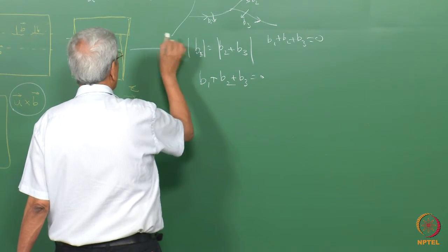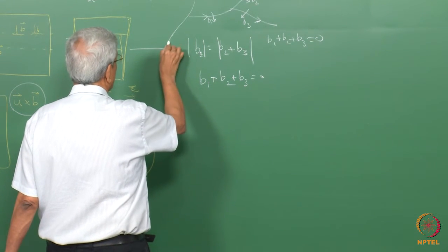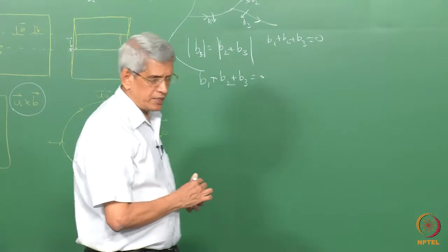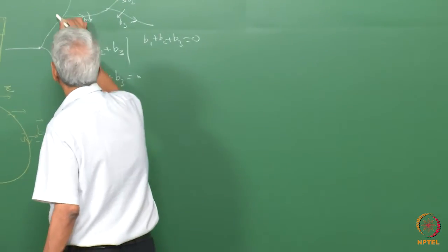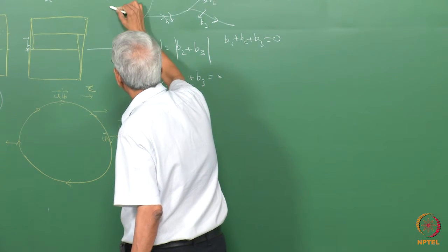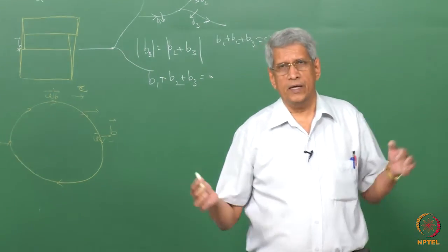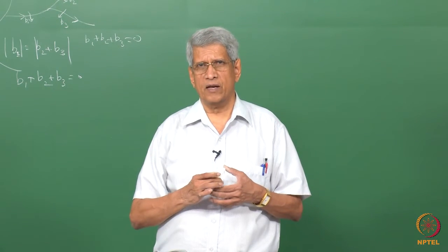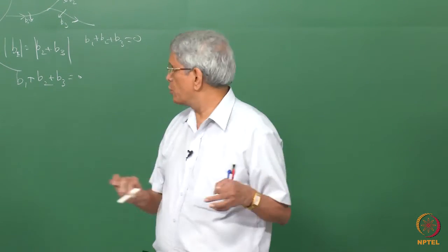Since they cannot end there, they have to join together at some point, so many junctions will be created. A single dislocation can only come out at a surface; it cannot end within the material. So the dislocation line should go from one boundary to the other boundary in a polycrystalline material, or, in a single crystal, from one surface to another surface.